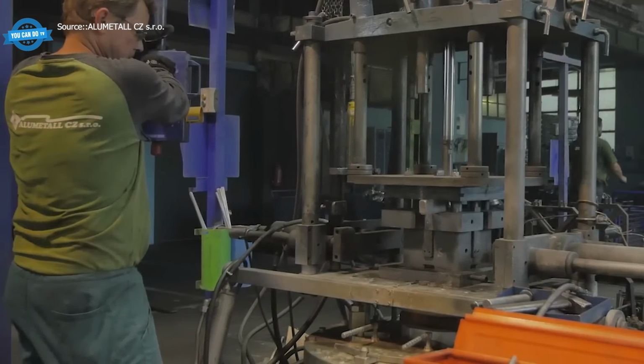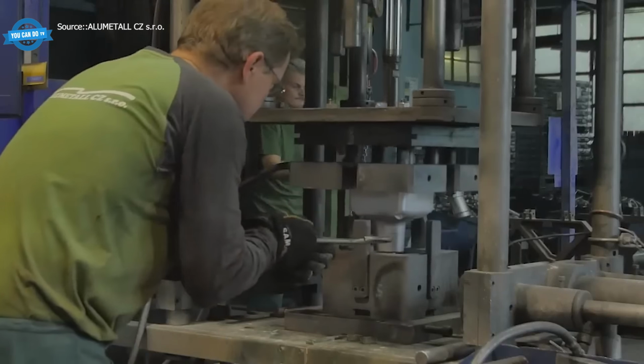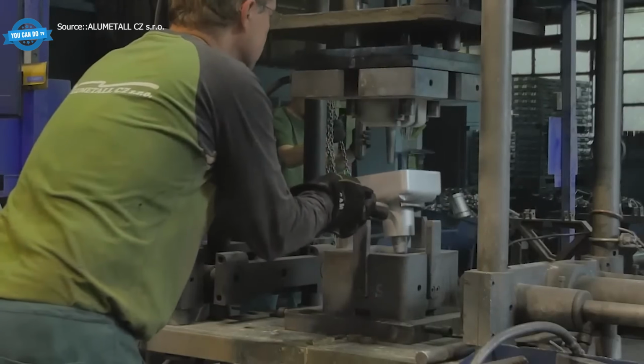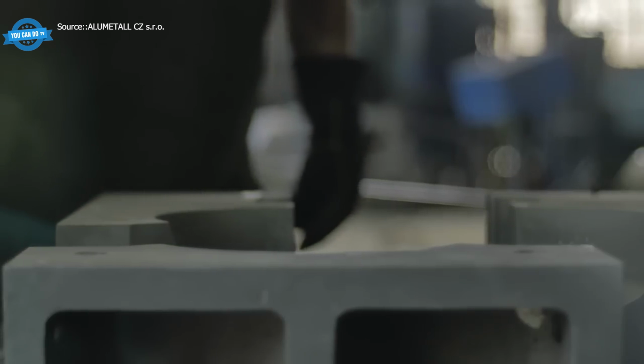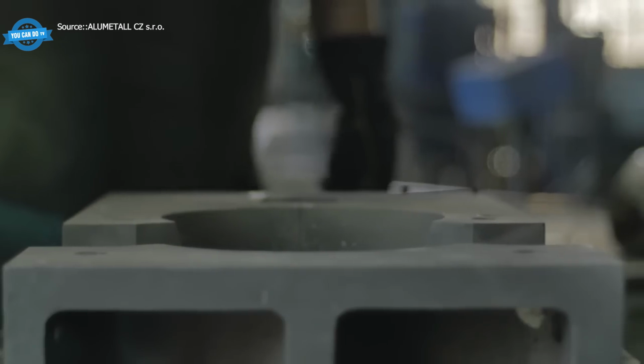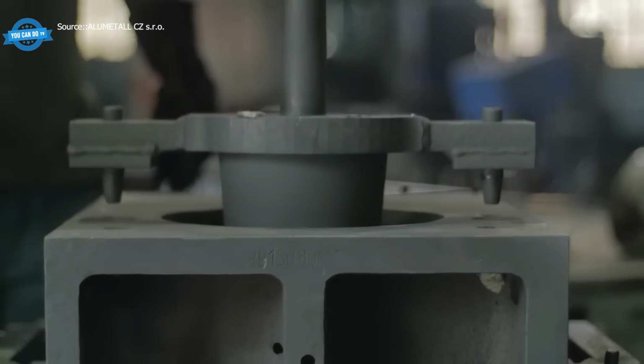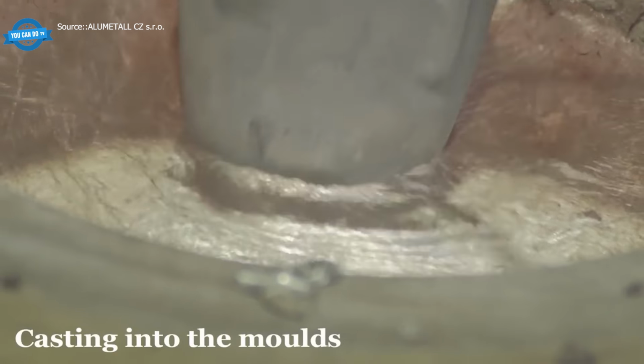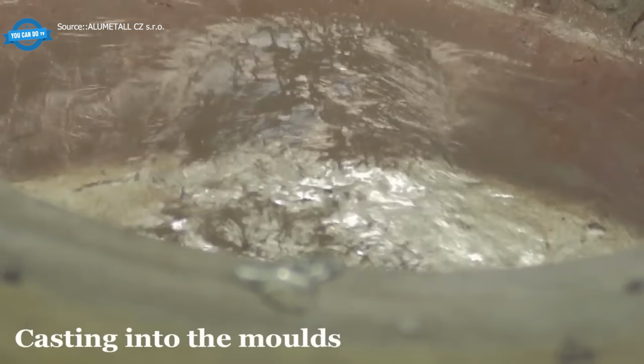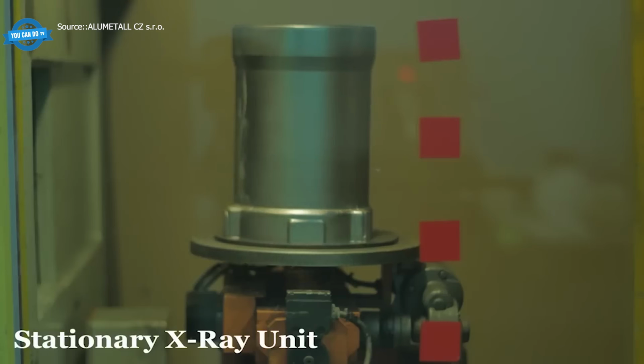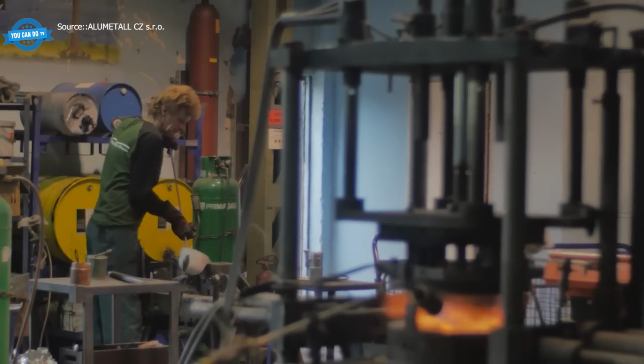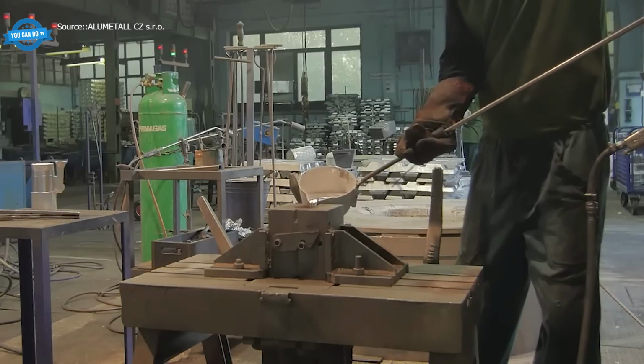Low-pressure casting machines fill steel molds with molten aluminum pushed up from below under controlled pressure, slower than die casting, cleaner than gravity casting, and better for structural parts that need to hold pressure. The upside is beautiful castings. The downside is a machine bigger than most people's houses that requires a dedicated maintenance crew. Each casting then heads to X-ray inspection. Anything with internal voids or porosity that exceeds spec gets rejected on the spot.